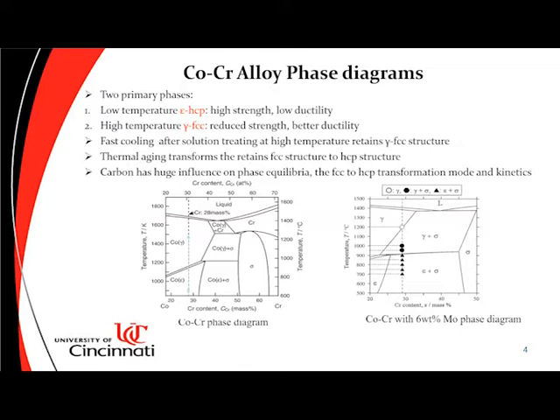In general, for alloy compositions with less than 38% chromium, there are two phases in this alloy, which are the high temperature FCC phase and the low temperature HCP phase. The FCC phase has relatively lower strength but higher ductility, while the HCP phase has higher strength but lower ductility. Fast cooling this alloy after solutionizing at higher temperature, usually in the FCC region, retains the FCC phase. And therefore, isothermal aging of this structure transforms the FCC phase to the HCP phase. And this is usually done at around 790 degrees Celsius. It is important to note that the addition of molybdenum shifts, as you can see here, the phase equilibria, and thus introduces a third phase, the sigma phase, which is quite detrimental to the properties of this alloy.